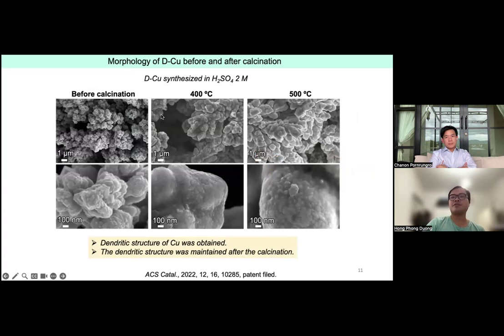I should have shown you this as well. By morphology, you can see that even going to higher calcination temperature, the dendritic structure was always maintained, except that the primary particles slightly change, which also makes sense because this is very usual in inorganic material. When you perform calcination, you have different morphology, edge, different particle.